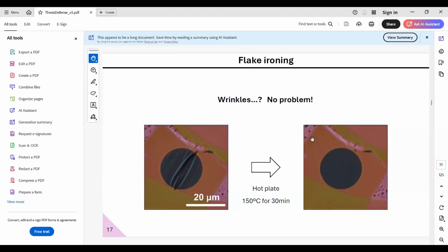Okay. Yes, I think it's a very good point, and I don't have an answer with results that support it, but I would expect that if this oxidation has occurred, it has occurred before we perform the actual measurements, because we left the samples in air, and we put them in and out of the desiccator for several characterizations. So we never made a flake and measured it 5 minutes after we prepared it. I could imagine that if it would have a strong effect, our flakes would also show a much different trend, because not all of them were heated to flatten again.